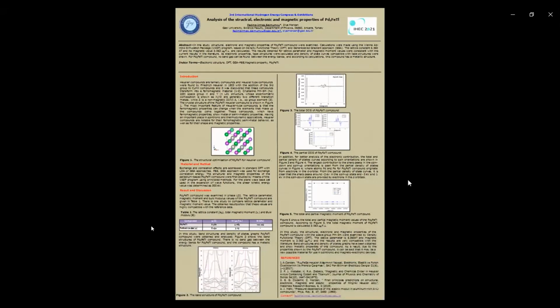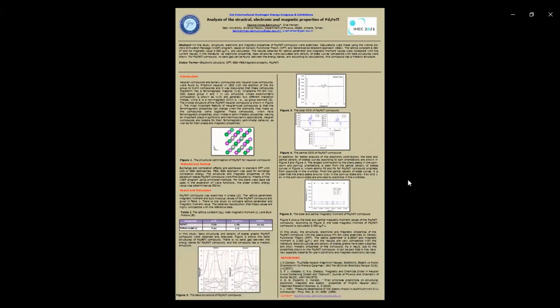In this study, the structural and magnetic properties of this compound were investigated with density functional theory. The lattice parameter is 6.360 angstrom, and the magnetic moment is 3.063 Bohr magneton per formula unit, respectively. Band structure and density of states graphs have been obtained and show the metallic properties of this compound.